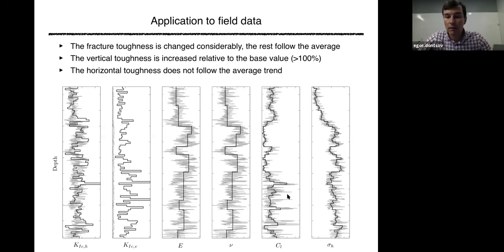It's okay to use average for leak-off and stress, right? But the biggest difference is fracture toughness. Again, both horizontal and vertical. Horizontal toughness, because we average energy, right? Again, we don't simply follow the high resolution data. Actually, what I didn't say is that high resolution is gray and low resolution is black right after homogenization. So we're not precisely following the curve here. And for the vertical, it's a big change, right?